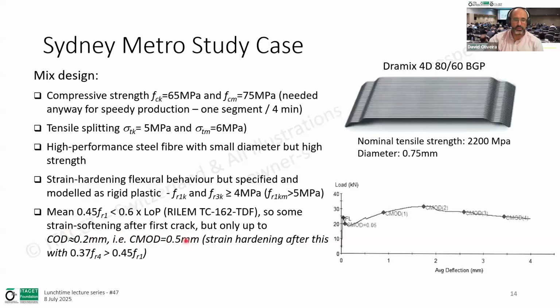So the crack mouth opening of 0.5 in flexure would be in direct tension more or less equivalent to a 0.2 millimeters COD. It would provide a small strength softening within that first region, but right after that 0.2 millimeters COD, it would start hardening again, because we were achieving in our mix ULS values, so FR3 and FR4s, that were greater than the equivalent axial tensile strength stress estimated from the flexural results.